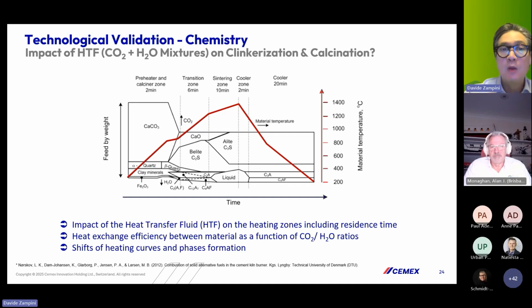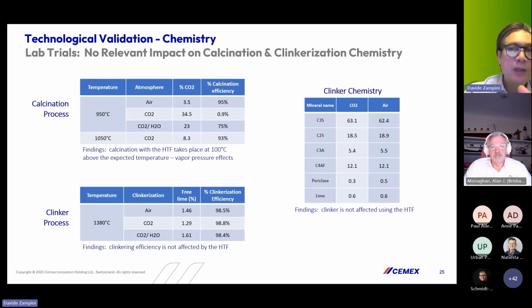Would it be the same, or would we completely alter the way we would actually achieve clinker, or are we going to change completely the chemistry, and what would be the heating curves? When would the phases form? So many questions, right? Without going into the details, basically, we tested in the lab. We simulated mixtures of H2O and CO2 vapor, and we took that up to 1,500 degrees. How would it affect the calcination process?